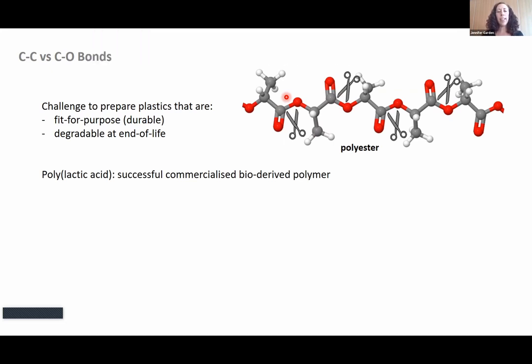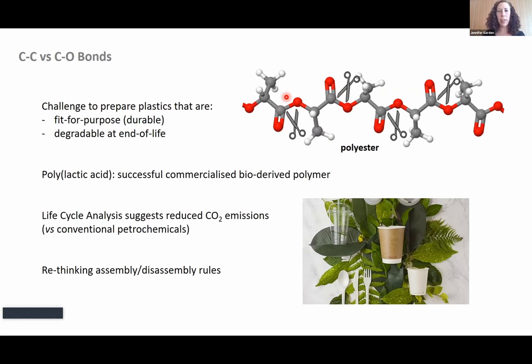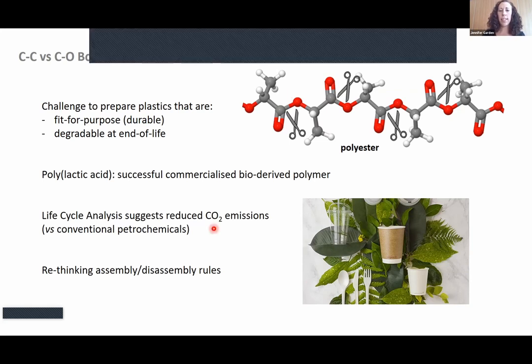And life cycle analysis has been done on this material. So as Alex highlighted, the importance of life cycle analysis. But what's quite nice about this material is that these studies suggest that it produces less CO2 emissions than conventional plastics like polyethylene and polypropylene. But what's quite interesting about this material is really that we can view it almost as a concept piece where you can reversibly make and break some of the chemical bonds in this structure to form this polymer material.